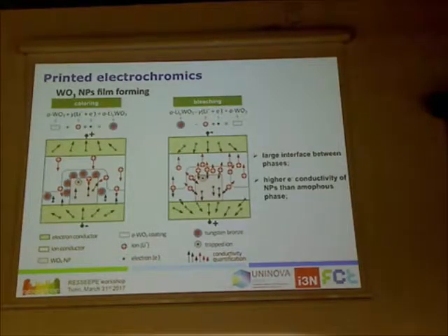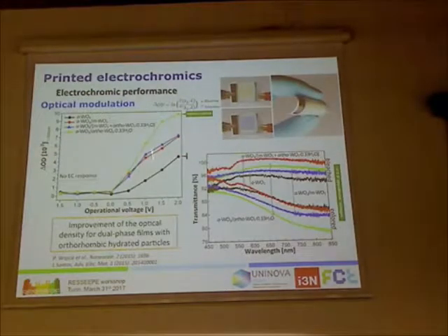What we have made is a simple test to look at the optical density for the same voltage. The optical density is the change in transmission of light at a certain wavelength between what we call the transparent or bleached state and the color state. You make the difference, and you see that for the same voltage, the best performance comes from this dual layer of amorphous coating over the nanorod particles. It's for the same voltage where we get the highest modulation between the transparent and color state. So comparing with just amorphous, or with dual phase layers using other particles, we see that this is better.